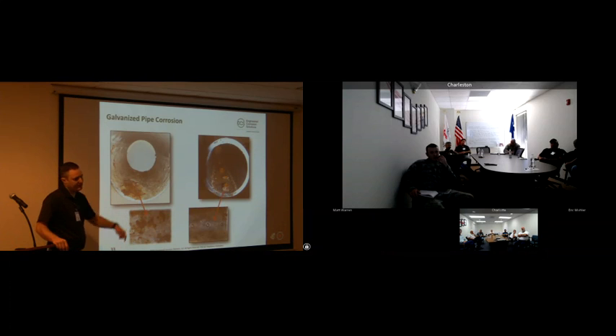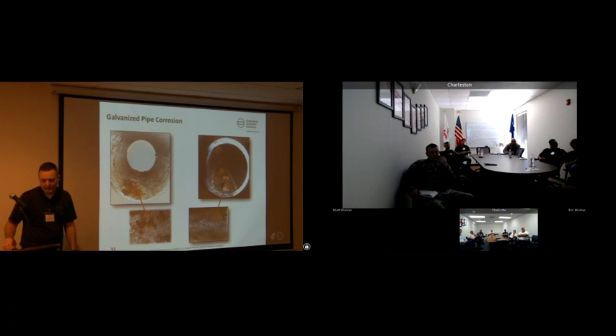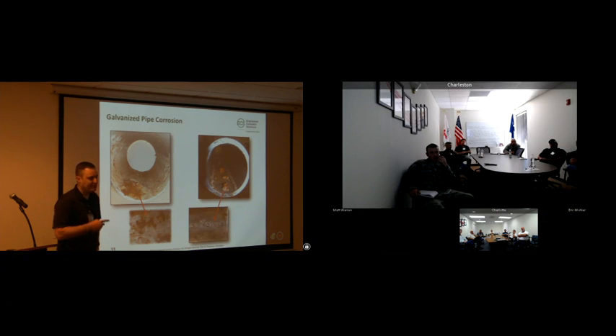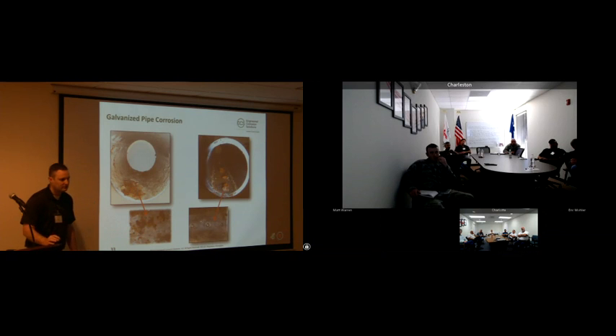That piece of pipe on the right came from DFW Airport. They put in a dry system and they said, you guys, we believe in what you're doing. We're gonna let you do anything you want with this dry system. So what we did was we put 4 vents on this dry system. We ran 98% nitrogen through it for over a year, about 18 months. After 18 months, we had spools at different parts of the system. We took them out, and this is one of those spools. This is not what we would expect a piece of pipe to look like with those pits that are about 50% wall loss after being under a nitrogen environment for 18 months.